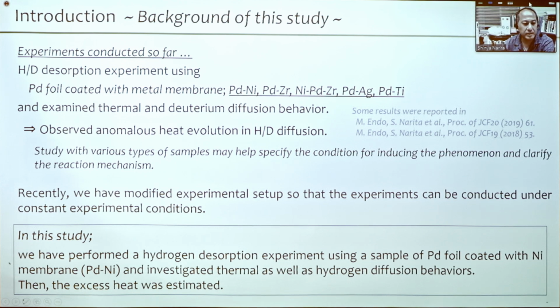And now recently we have modified experimental setups so that the experiments can be conducted under constant experimental conditions. So here in this study, we have performed a hydrogen desorption experiment using a sample of palladium foil coated with the nickel membrane, also called palladium nickel sample, and investigated thermal as well as the hydrogen diffusion behaviors. Then the excess heat was estimated.